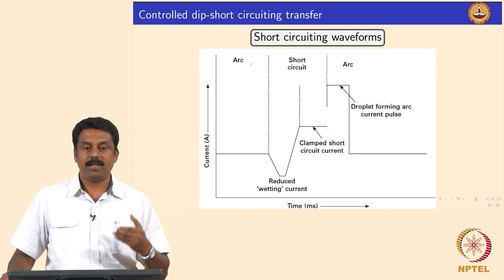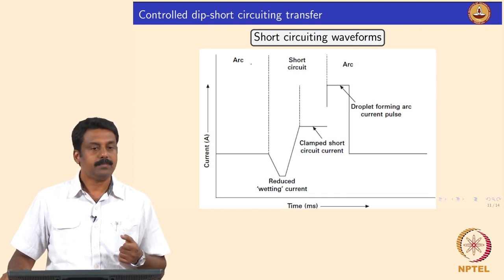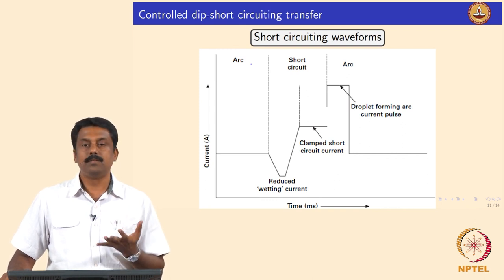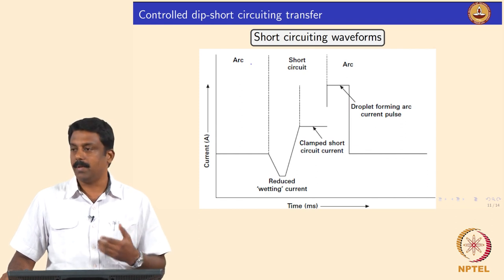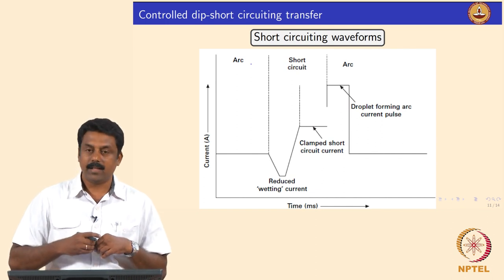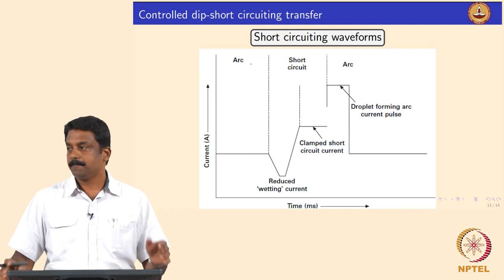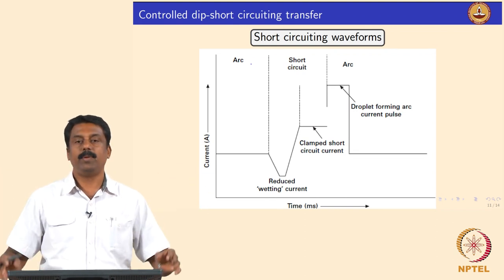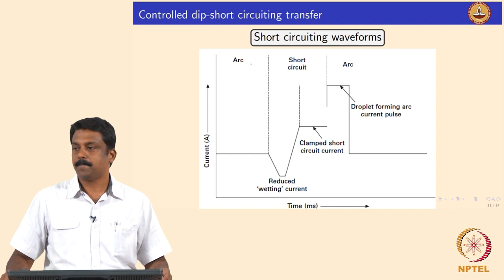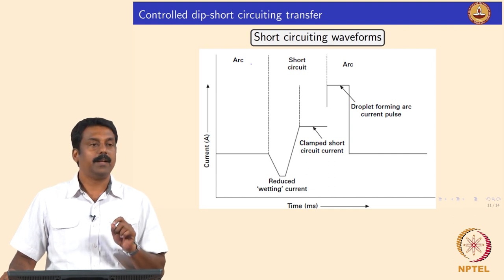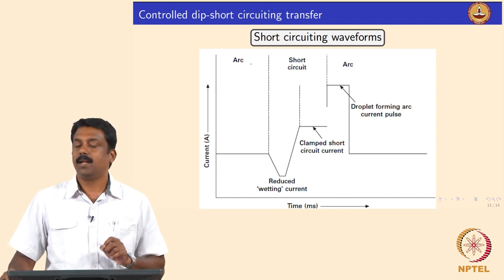Because you have a bridge forming between two solids — a liquid bridge with extremely poor electrical conductivity — the accumulation of charge carriers at the droplet leads to an enormous amount of Lorentz force and magnetic fields. The moment short-circuiting happens and the force accumulates, it leads to the explosion of the droplet, causing severe turbulence in the weld pool. Whatever melts gets thrown to various places, and that causes spatter. So we need to identify some mechanism to avoid such an unstable process and metal transfer characteristics.